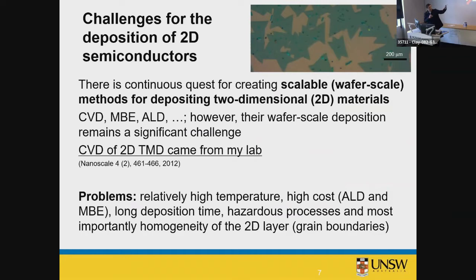The problem is you always get these triangles. The size of triangles are large, sometimes go to 300, 400 micron, but still is not wafer scale. The center is always a seed which is very thick, and these triangles go on the top of each other, make double layer, or in the best case, they stitch together at the corners. So when you have electrons, they reflect, they scatter from those stitching points. It's not good. Other methods like MBE, MOCVD or ALD, you can use, avoid the stitching, but they are cumbersome, high vacuum, other problems.